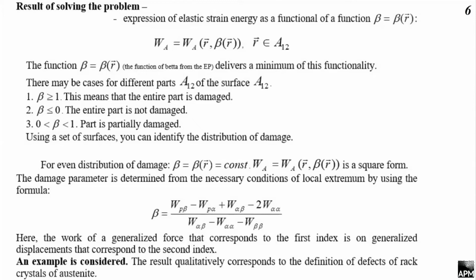For even distribution of damage, beta is a constant. W is a square form. The damage parameter is determined from the necessary condition of local extremum by using the formula for beta. Here we have a generalized force that corresponds to the first index and a generalized displacement that corresponds to the second index. An example is considered. The result corresponds to the definition of defects of rack crystals of austenite. Thank you for your attention.